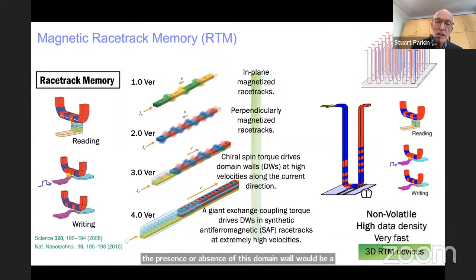And furthermore, by passing current pulses into this racetrack, we can move all the domain walls synchronously in the same direction, backwards and forwards, and bring these walls to elements that would be designed to read, and that would be designed to write the domain walls into the racetrack. So this is what I proposed. And I said, look, this is non-volatile, could have very high density, could be very, very fast, and could enable us to replace the magnetic disk drive that today uses a spintronics sensor that I invented many, many years ago, and magnetic disk drives store 70% of all digital data today. Maybe we could replace it with a racetrack, which is non-volatile, non-mechanical, and therefore more reliable and would be much faster. So this is what the proposal was.